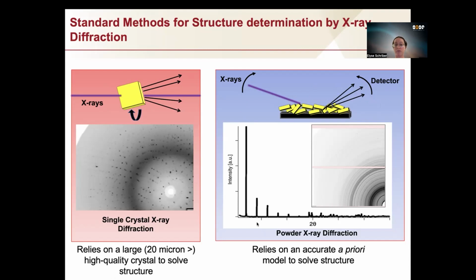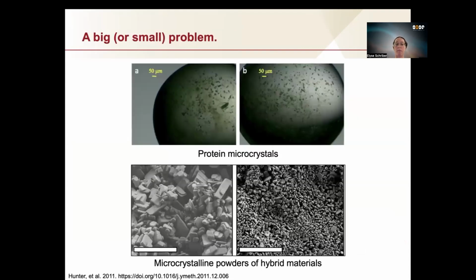Now, one can determine the 3D structure of a material from this, but you have to have an accurate a priori model to be able to solve the structure, which relies on accurately modeling the position of the intensities and the intensities themselves. Both of these methods highly rely on two different things: large, high-quality crystals or having some kind of a priori model. There tends to be a big problem with both of these methods, in that a lot of crystal materials, new materials and proteins, don't actually crystallize to become large single crystals, and we also don't have a priori models of them. They are new materials, they are unknown proteins, and the problem with this is that we can't use these standard known techniques.